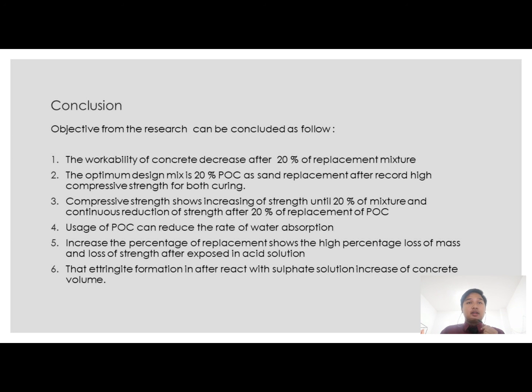For the conclusion, firstly, the workability of the concrete decreased after 20% replacement mixture. The workability of the concrete is over the target slump. For the second conclusion, the optimum design mix is 20% of POC as sand replacement, after recording high compressive strength for the water curing.